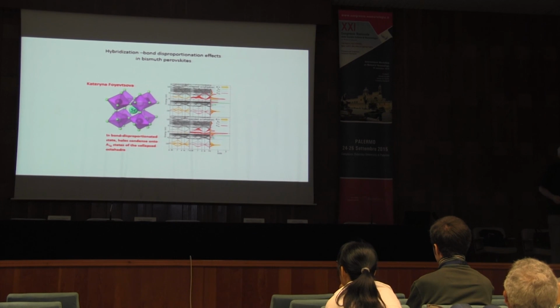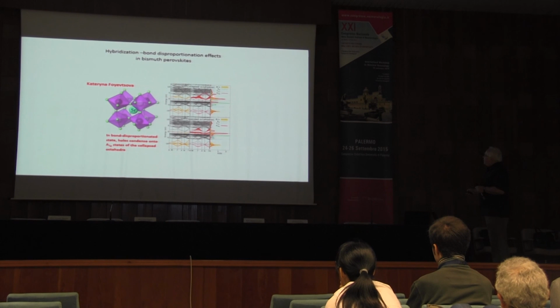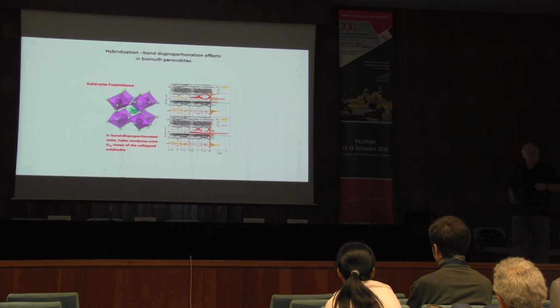And you've got to be careful with this, because the U on oxygen is 4 electron volts. It has been measured with Auger spectroscopy, so it's not negligible at all compared to this band. So maybe there is a correlation problem in the end. Who knows? Anyway, this is a very narrow band. There is a gap formed over here, but that only occurs if indeed you have, again, this bond disproportionation. Long bond lengths and short bond lengths alternating. And that is the right structure for the barium and strontium bismuth-O3.